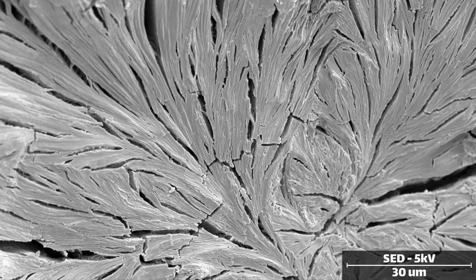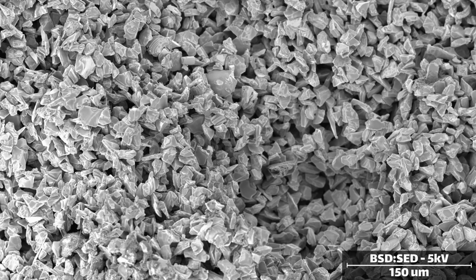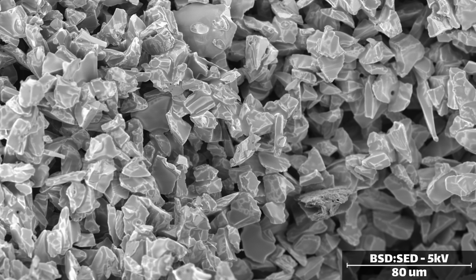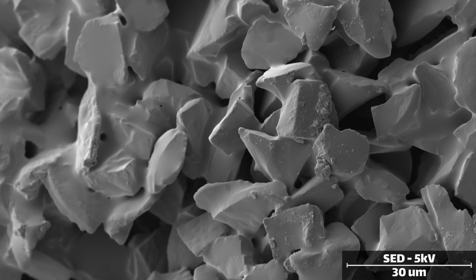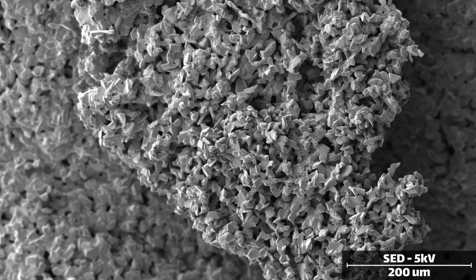And that's the starch that has been polymerized out and then dried in place, and it forms kind of this filamenty, muscly fiber network. In contrast, when you look at a sample that's been fired at 600 degrees, you see all the filamenty starch stuff completely go away. It's gone no matter where you look, and you're just left with the silicon carbide grains and that kind of liquid looking surface in between all the grains holding everything together.